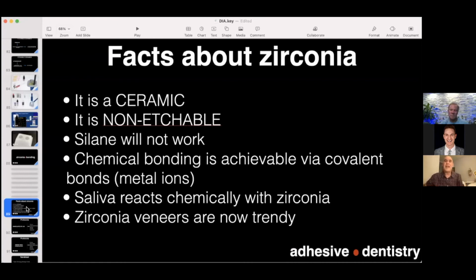Now, here is a caveat. Saliva will not react with anything, with dentin, enamel, lithium disilicate, titanium, nothing. But it will react with the zirconia, 100%. And when it reacts with zirconia, it will deplete the bonding sites. So once the zirconia surface has reacted with the saliva, you cannot bond to it. So this is something to consider, okay?